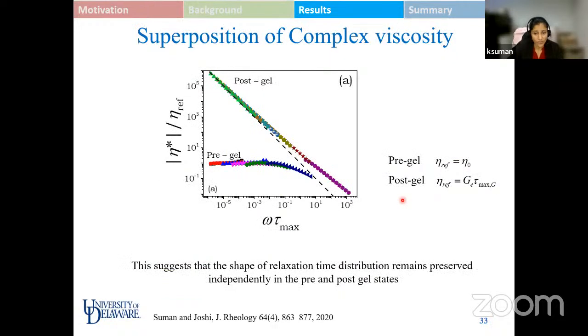So with this, we also have another advantage, that is it can lead to superposition of complex viscosities. So in the pre-gel region, we did experiments at different times, and now we can superpose all those data using the different parameters, and it all gets superposed very nicely into two master curves over here, one corresponding to the pre-gel region and the other corresponding to the post-gel region.